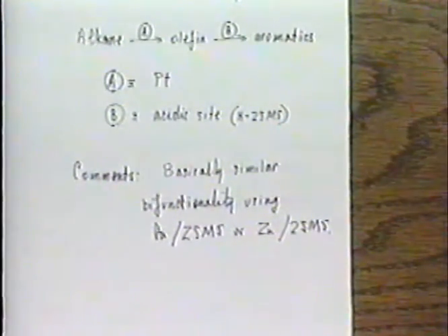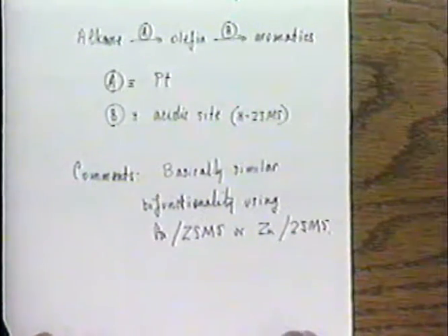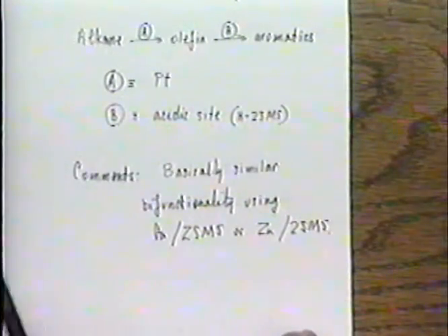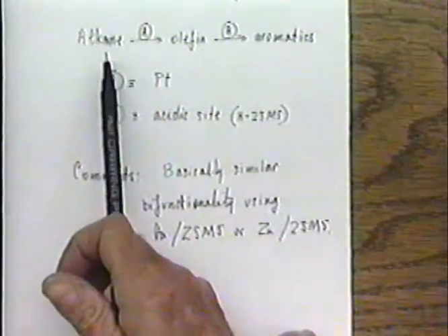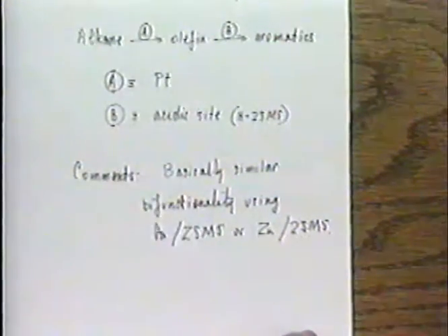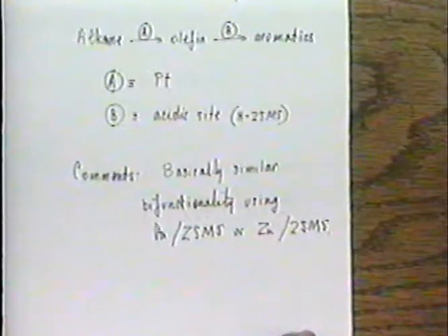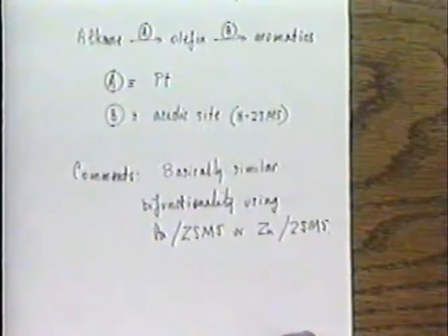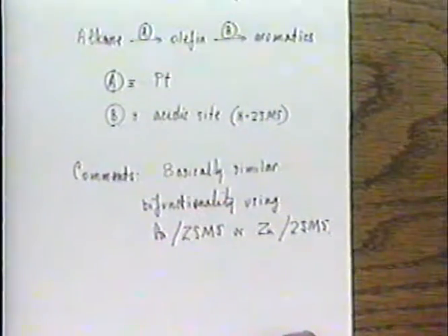It's, I suppose I should say, teetering on the brink of commercial reality, because it offers a way of converting a gas like propane to aromatics, and the aromatics may well be required as a fuel blending agent. And if one started with propane, the sequence, which one would have to elaborate a little bit here, would be propane to propylene over the platinum function, dehydrogenation, propylene to higher olefins over the ZSM5 function by oligomerization, then cyclization and dehydrogenation also in the zeolite function.